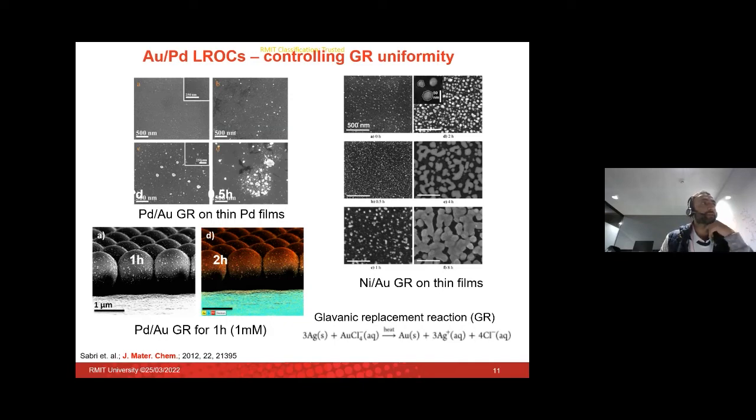We've done this now on a colloidal structure. What you see now is that we can actually get a more uniform structure over the surface. So on top of each colloid, each one is now acting as a reactor system. So all these particles are growing equally onto each of the colloidal particles, right? From close range, you could still say that it's not uniform, as Antonio Charcoli was talking about before with his structures. That's true. At close up, it might look a little bit disordered, but when you look at it at a large, long range image, then you'll find that it's an ordered structure. So you're still getting a reproducible surface.